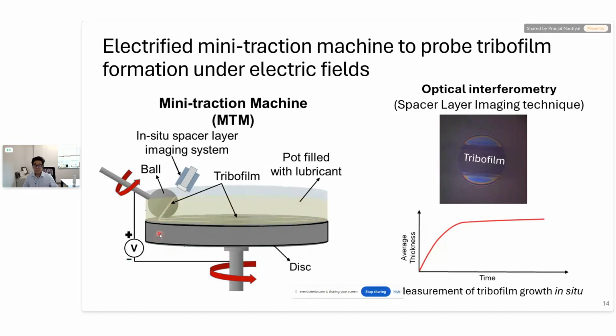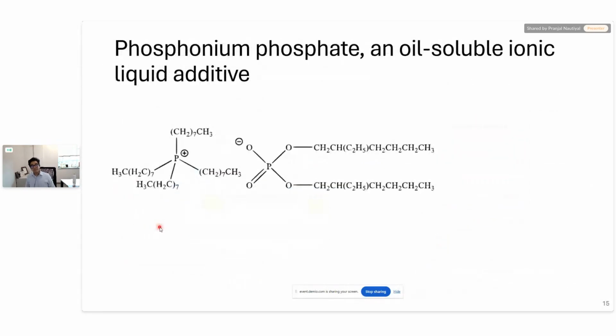So unlike traditional MTM, we used an electrified MTM in our experiments. Essentially, we pass electric current through the ball disk interface. As you can see, it's an electrified MTM. We can pass currents through the interface, and that allows us to study the formation of tribofilms and the growth kinetics of tribofilms in the presence of electric fields, which we hope will help us develop fundamental insights into these tribofilm formation mechanisms. So for this study, we investigated a phosphonium phosphate ionic liquid.